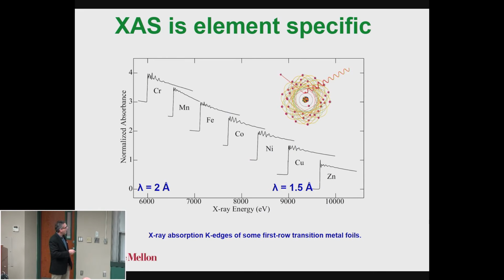So if I just collect data over that energy spectrum, I'm only seeing chromium. Or I'm only seeing iron if I'm in this spectrum. So no matter what's in your sample, no matter how much metal, sort of, a caveat to that: if you're using fluorescence, everything fluoresces, you have to watch out for that. But if I'm interested in a specific metal, I can look at just that metal. That's what's really great about X-ray absorption spectroscopy.